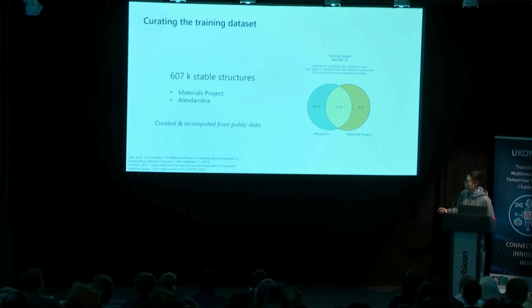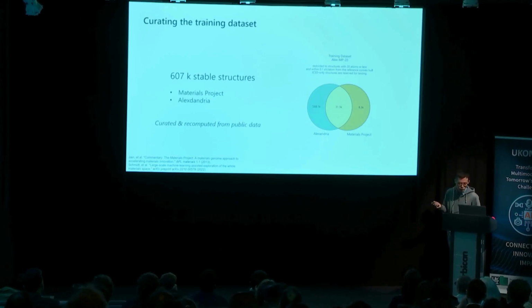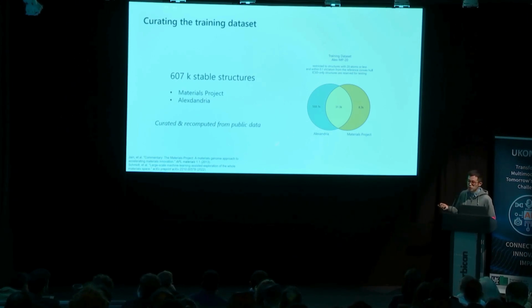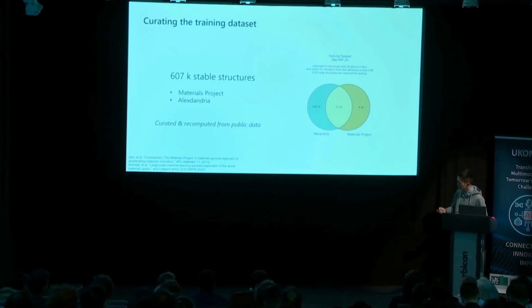We collected all this from public data, but the key thing we did is that we ran quantum mechanical calculations ourselves. At the beginning, there are maybe around 3 or 4 million of these data points, but by running calculations, we remove those unstable points. Therefore, this only leaves the stable materials, and we found that having only stable, high-quality materials is very helpful for the model performance. And this gives us a data set of around 600,000 structures.